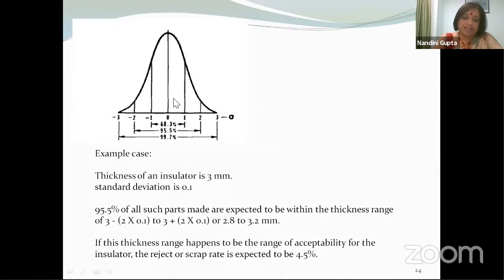Another thing is that for most normal distributions, you can decide what is the confidence interval. Let us take this example case. We find that 95.5% of all data is expected to lie within plus minus 2 sigma, which means that suppose this is data pertaining to the thickness of an insulator, and you're making this insulator and you're expecting the insulator to have a thickness of 3 millimeter, and that is your desired objective. And let's say it has a standard deviation of 0.1. Then you will find that 95.5% of all such parts made are expected to have a thickness in the range of 2.8 to 3.2. So that is the deviation that you expect.